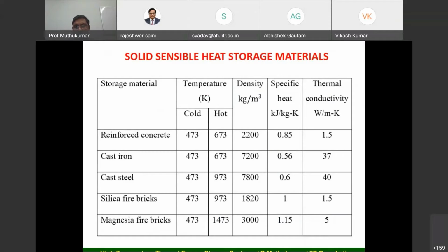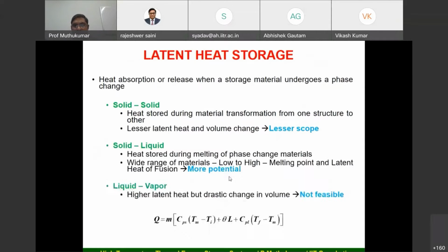We have done quite a lot of experiments with the concrete, and we didn't face any kind of thermal cracking issue. But the only thing is, when you are choosing the concrete composition, you need to be very careful. And the magnesia-based bricks are again an interesting material if you are looking for temperatures above 1000 degrees Celsius. But there are issues which need to be discussed. Mainly, its density is relatively low compared to cast iron and others. That can, of course, be improved.